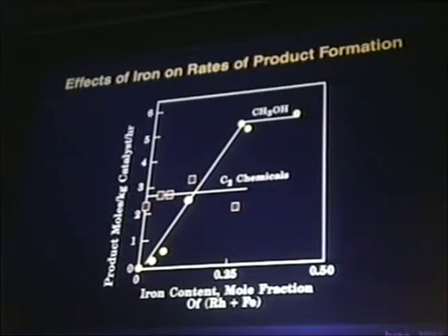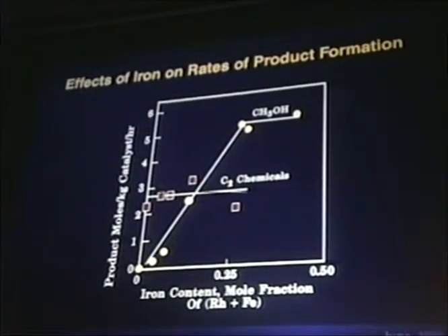As you can see, the total C2 production on this rhodium-iron system is essentially constant, although you could make a small case for some increase in the C2 chemicals from zero to about 0.1 mole fraction, and then coming down as the iron begins to dominate the catalyst system. But the methanol production increases in a straight line fashion up to about quarter mole fraction of the total rhodium-iron. Next one.